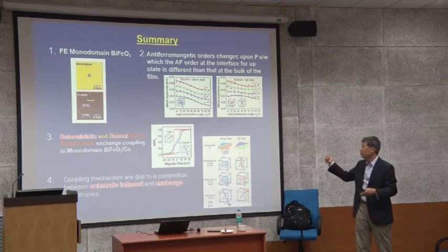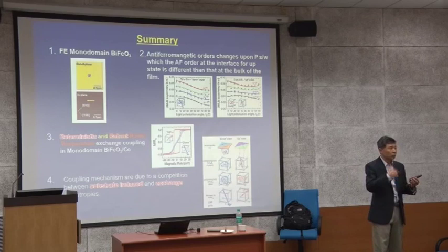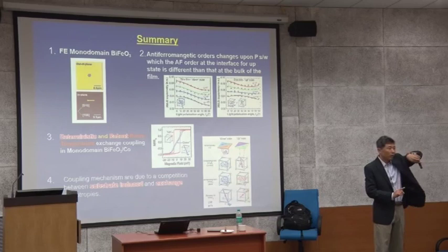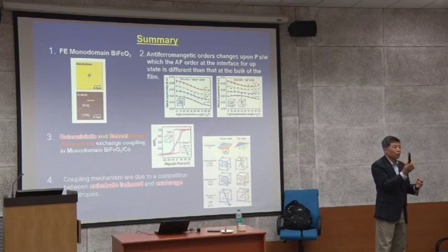That's why here, in a lot of measurements, we use X-ray diffraction and RSM, and then combine with PFM. PFM gives additional information because it's a ferroelectric measurement. For example, an X-ray diffraction measurement cannot tell this one from that one with a normal measurement, because the difference is very tiny. A synchrotron can do it, you know that. But with the PFM measurement, you know which one is which, while in X-ray diffraction the peak positions of this one and that one are almost identical.